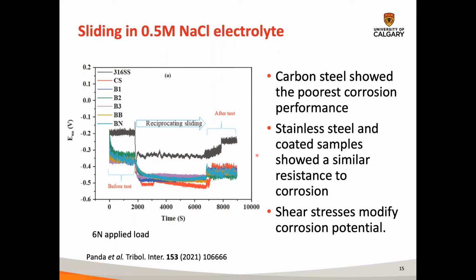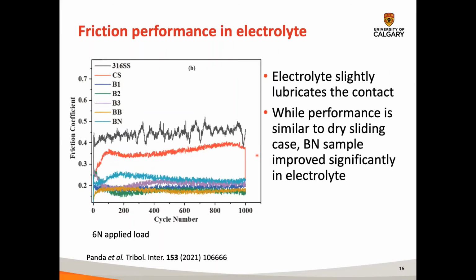fracturing applications. And then we can also measure the friction coefficient while we're doing these corrosion measurements, and we see here that the friction coefficient of the carbon steel increased significantly, and we see very low friction in these electrolytes of the boronized steel. And we still see that this boron enhanced top layer is really performing a lot better than all of the other coatings.